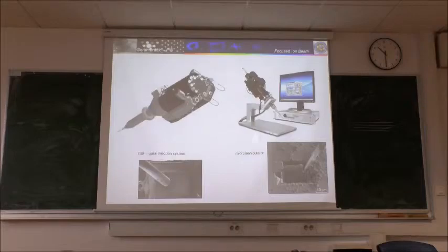Another part of this complete system is the gas injection system. This system ends with a very tiny capillary, I think some 100 microns or something like that at the end. And a certain gas, depending on what type of material we want to use, comes out from here. It's not blowing, but the partial pressure here is, I think, at least 2 orders of magnitude worse than around here. And why is this used? This is used for deposition. We will see later on how we can perform this process.